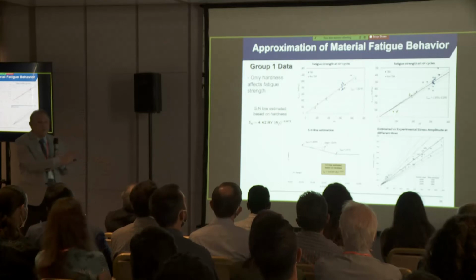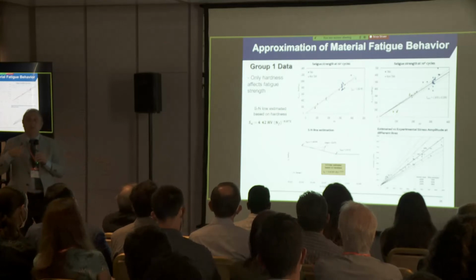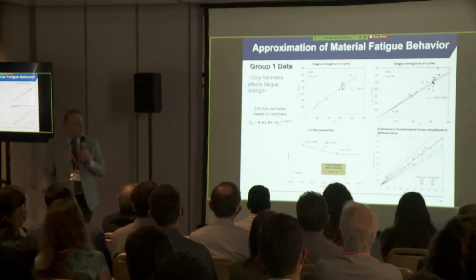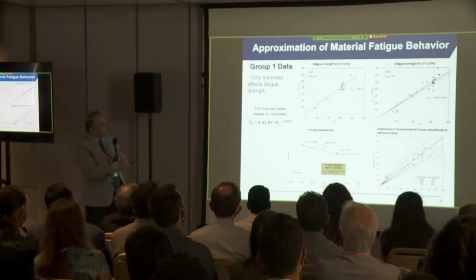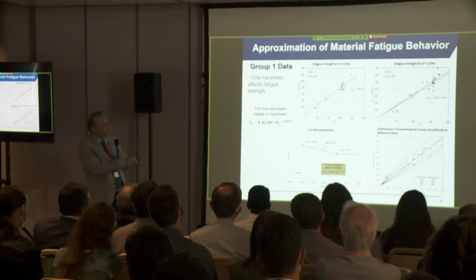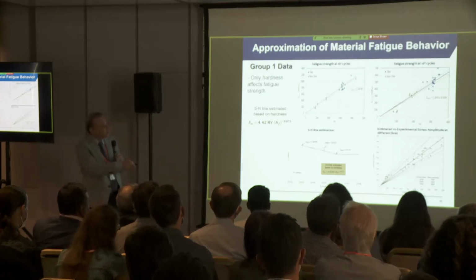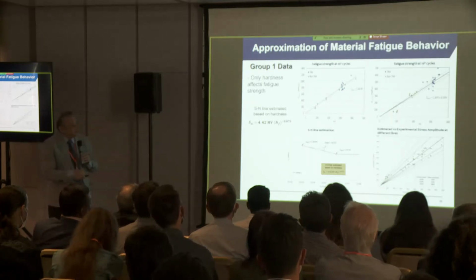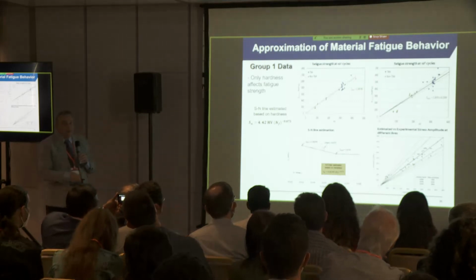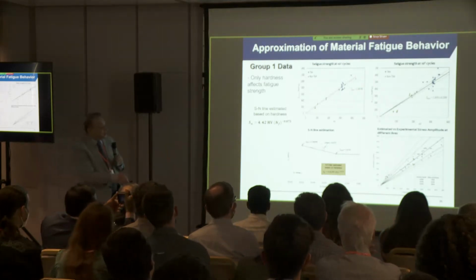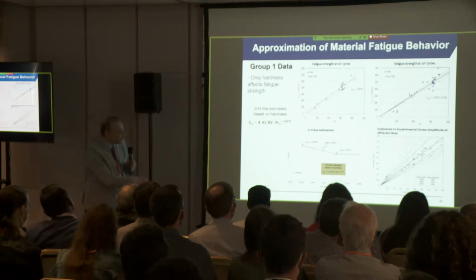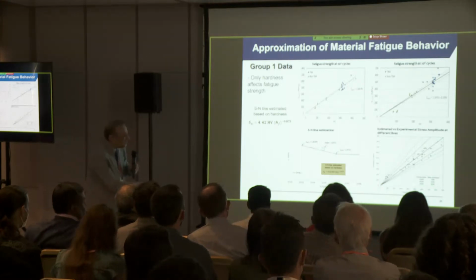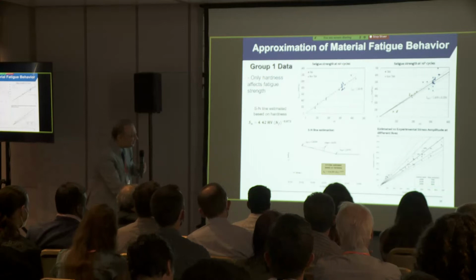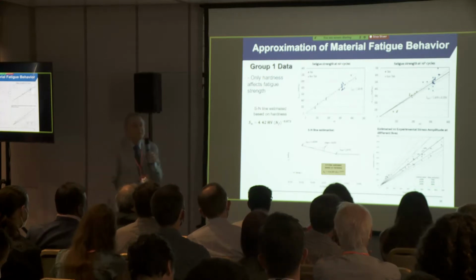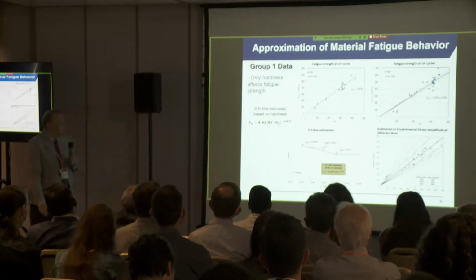So with the group 1 data, where defects or surface roughness does not drive failure, you can see good correlation for fatigue strength at 1,000 cycles versus hardness, and fatigue strength at 1,000,000 cycles versus hardness. Based on that information, you can construct an SN line. And this SN line can result in relatively good predictions. So 82% of the data were within, I cannot see the number there, 33% of the stress.